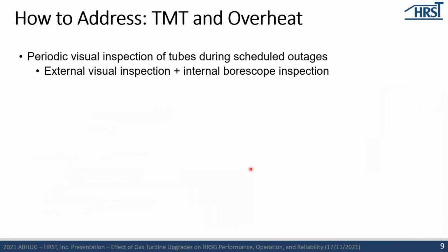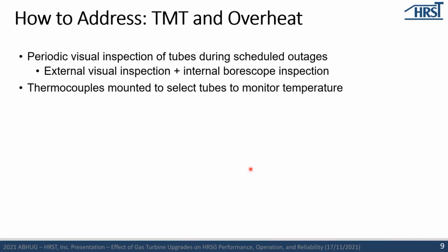So just a couple of ways to address tube metal temperature overheat. We discussed a few already. Periodic visual inspection of the tubes, external visual inspection, and internal borescope inspection, looking for any signs of oxide growth on the interior of the tubes. Thermocouples mounted to the tubes is a great way to monitor them. Typically, you need quite a few in the HRSG spanning the entire width because oftentimes a thermocouple will tend to fail. So being able to have that redundancy can give you that confidence that you're operating at the correct temperature.